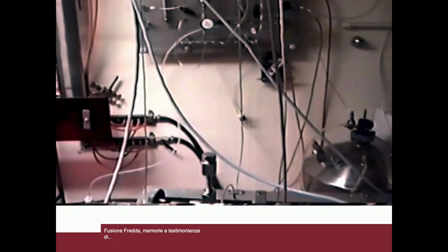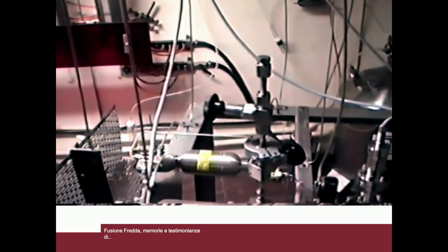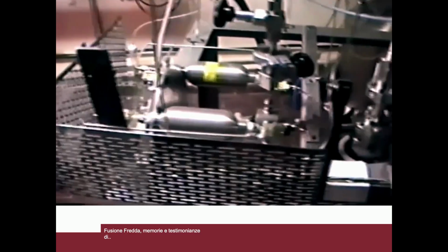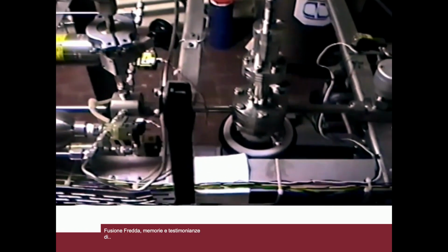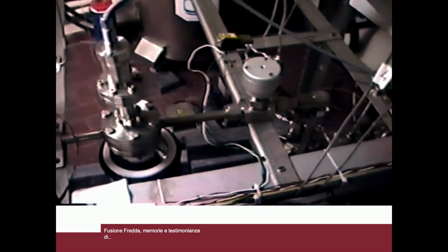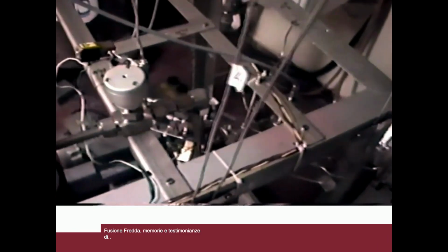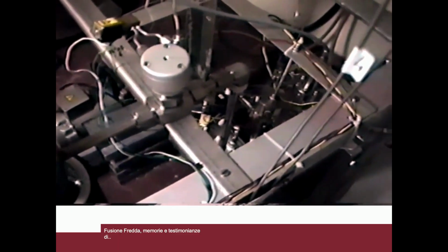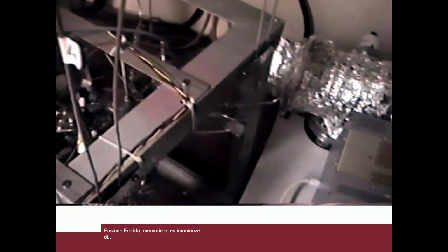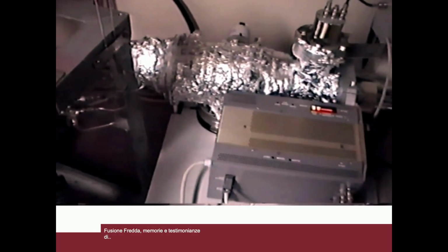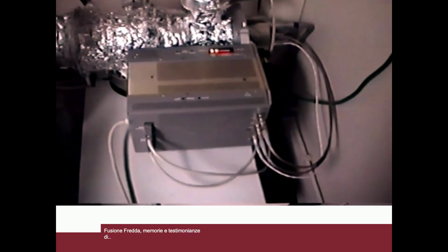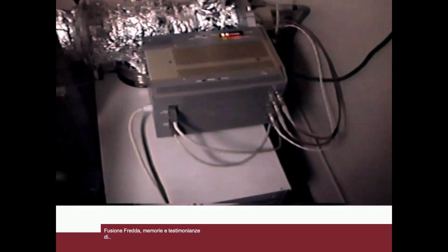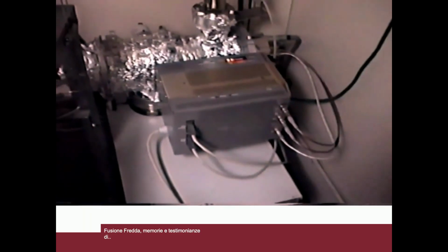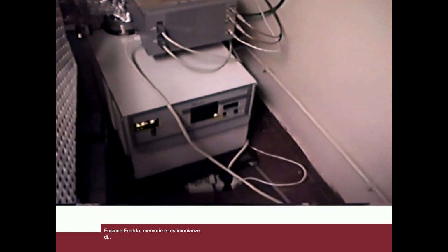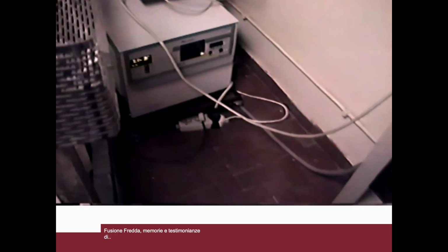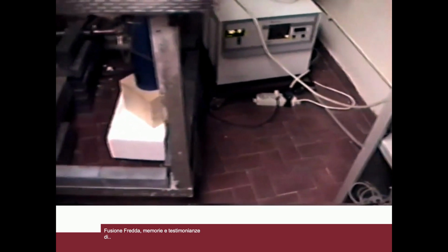Here the entire gas sampling apparatus is visible, which consists of an automatic system controlled by one of the computers to divert the gas flow of the cell under examination to the sampling. The visible stainless steel cylinders have a volume of 150 cubic centimeters. The collected volume is diverted to a stainless steel container filled with getter alloys and subsequently to another stainless steel container with activated carbon in liquid nitrogen, as visible in the blue dewar.